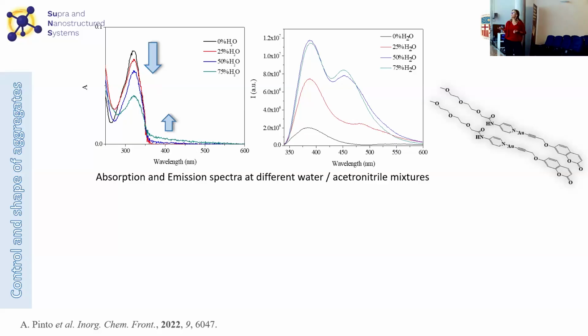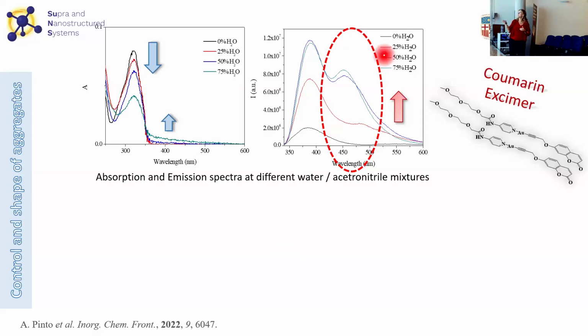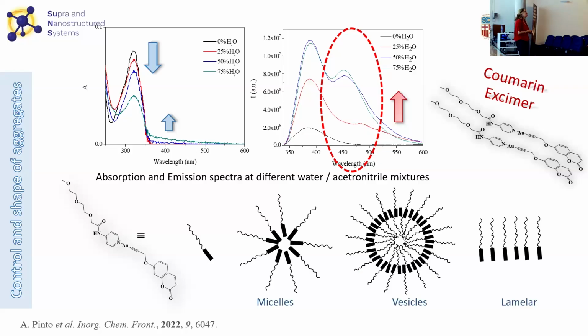Okay, the information that we retrieved from emission spectra was also complementary, since what we observed is that when we increase the amount of water, there is the presence of a new band at longer wavelength that can be correlated to the formation of some pi-pi stacking between the coumarin units. So there is a complementary formation: in fact, we have some excimers of the coumarin that are making these aggregation processes. So we know through these experiments that our molecule aggregates, but in fact we don't know exactly what type of aggregates we have. We can have some micelles, we can have some vesicles, we can have some lamellar aggregates, so we don't know what we have.